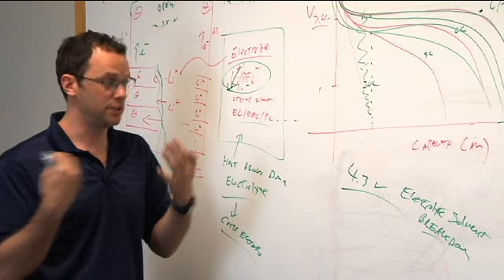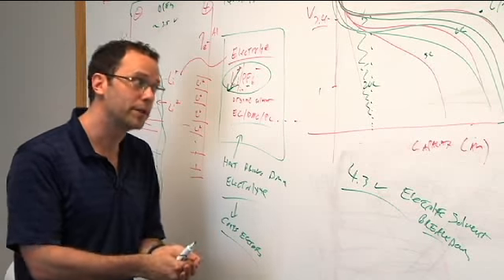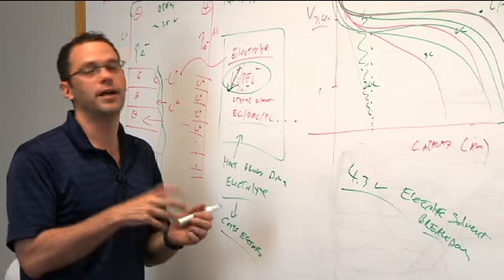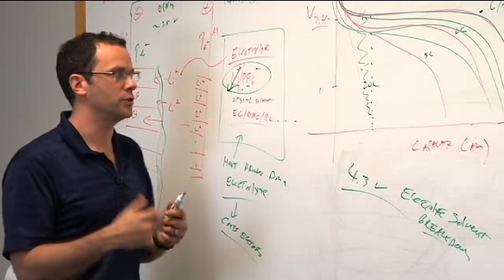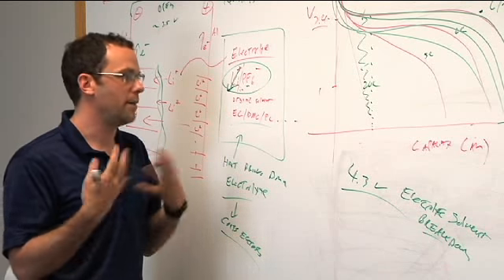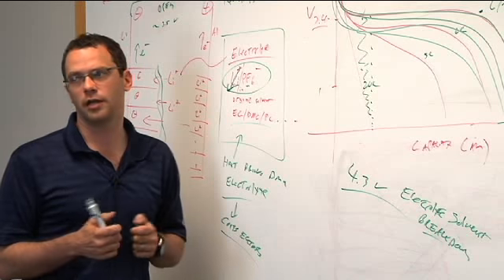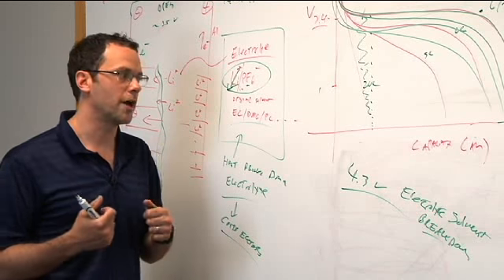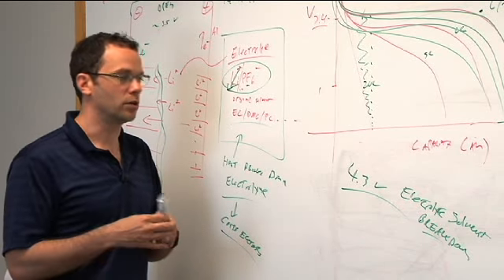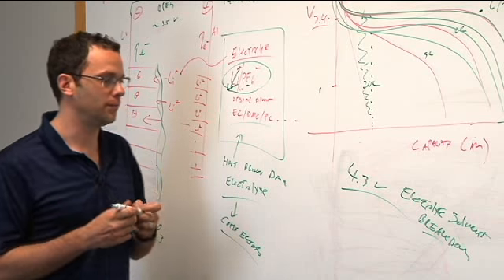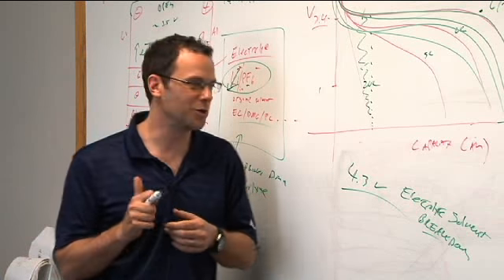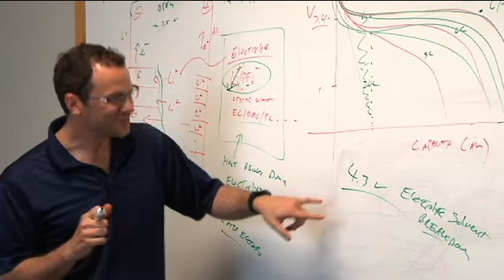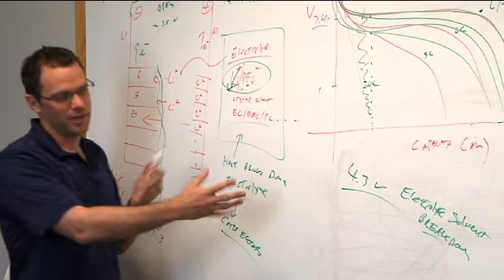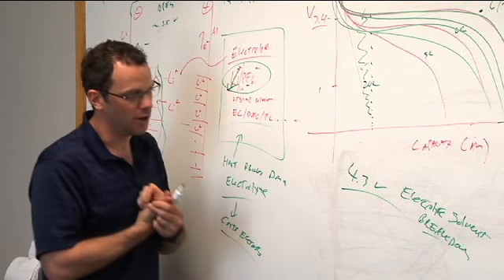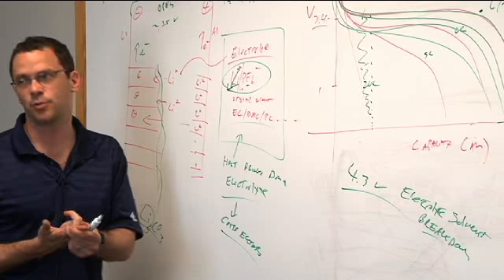When it evolves into gas, it pressurizes the cell, and there are vents built into all these batteries, all these individual cells. If it happens slowly, it will vent. It will be a benign loss of function. The electrolyte will dry out. If you do it too rapidly, you can cause what we call a rapid venting event, which is an explosion. And when that happens, the chance of a spark and subsequent ignition is much higher.